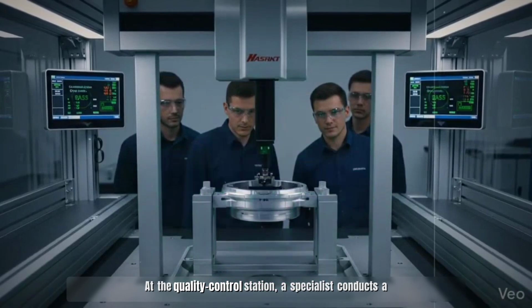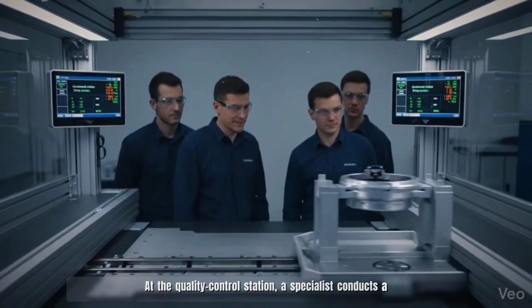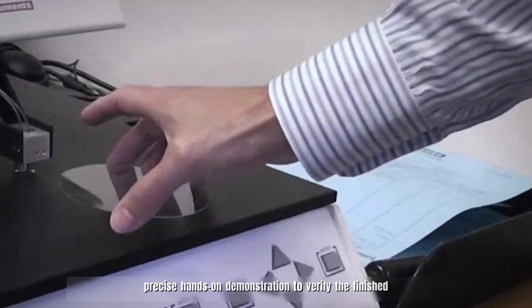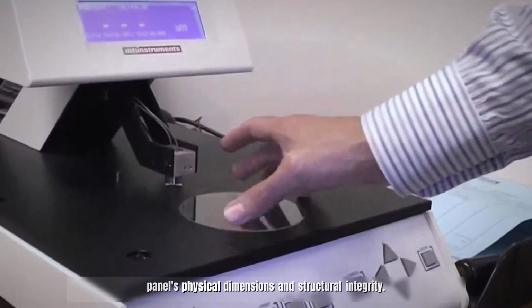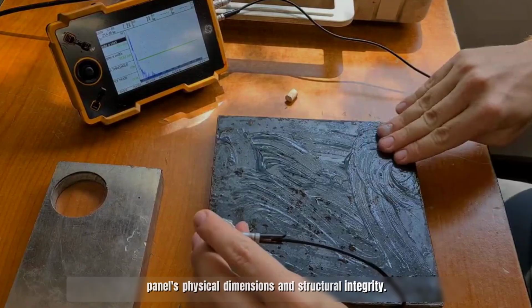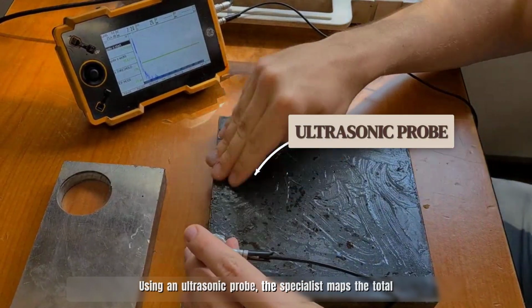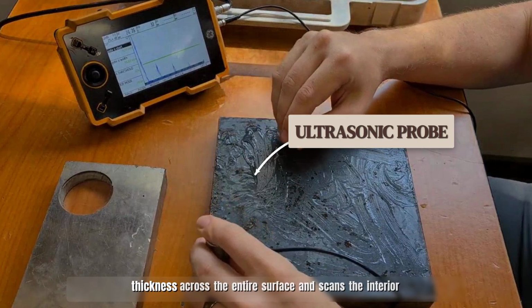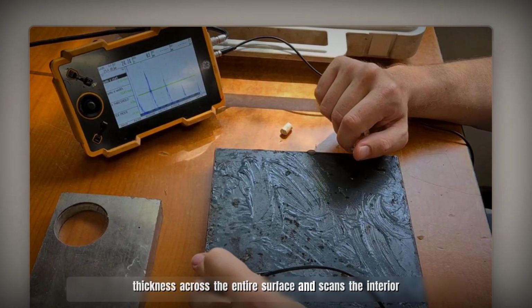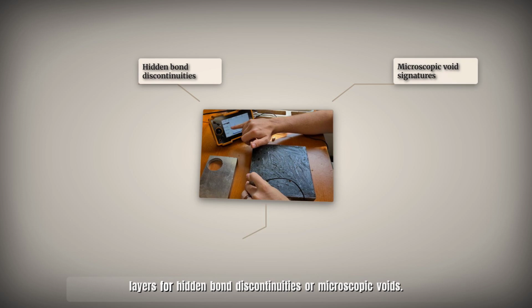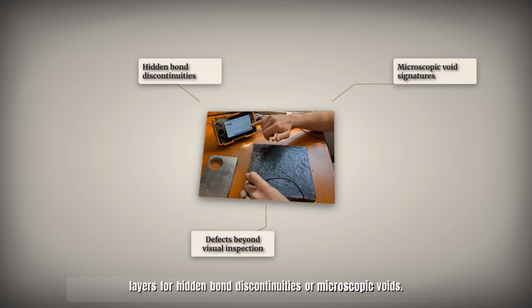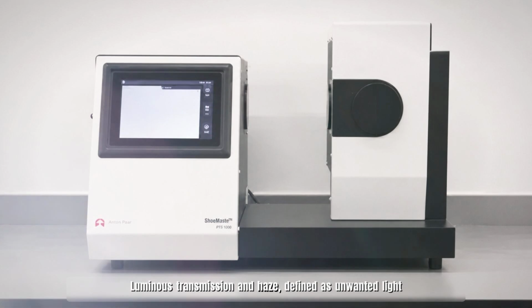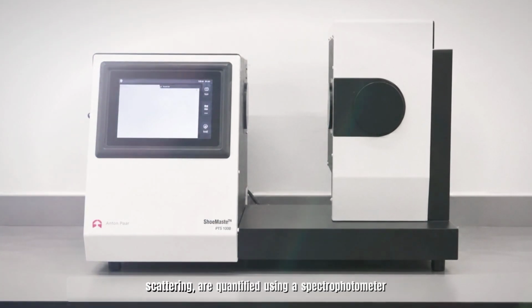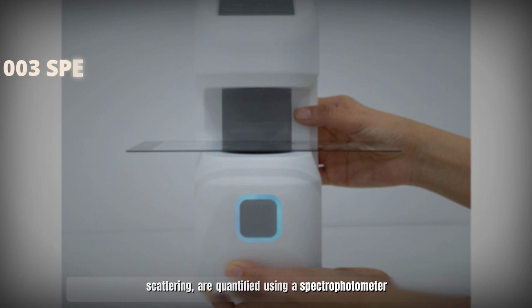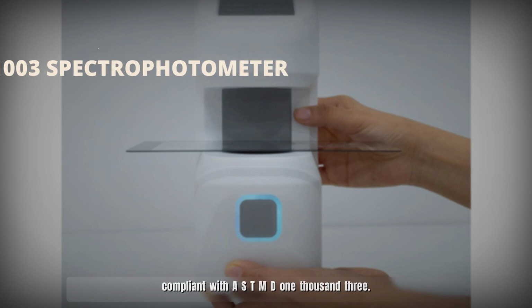At the quality control station, a specialist conducts a precise hands-on demonstration to verify the finished panel's physical dimensions and structural integrity. Using an ultrasonic probe, the specialist maps the total thickness across the entire surface and scans the interior layers for hidden bond discontinuities or microscopic voids. Luminous transmission and haze, defined as unwanted light scattering, are quantified using a spectrophotometer compliant with ASTM D1003.